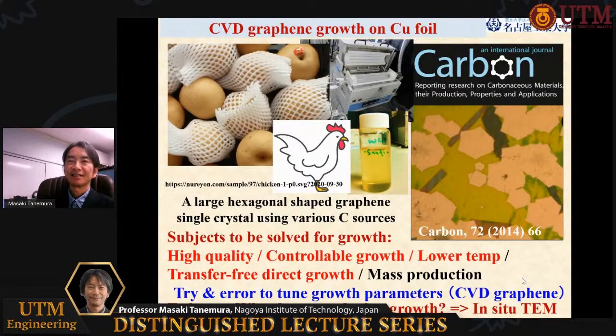Nowadays, graphene is one of the most interesting materials. Many researchers want to achieve the controllable growth of high-quality graphene at lower temperature directly on the substrate in mass production. Chemical vapor deposition, CVD, is a powerful tool for graphene synthesis, and tuning the growth parameters to achieve this goal is very important. Of course, we are doing this optimization, sometimes by using such funny carbon sources like waste polymers and chicken fat. Actually, very high quality single-layer graphene grows using those carbon sources like this.